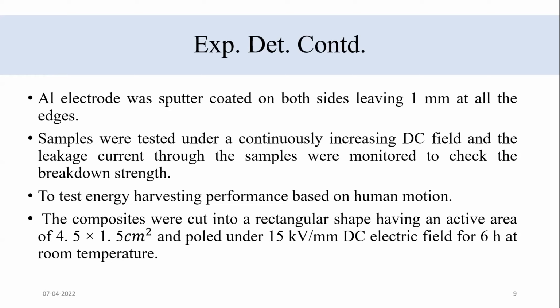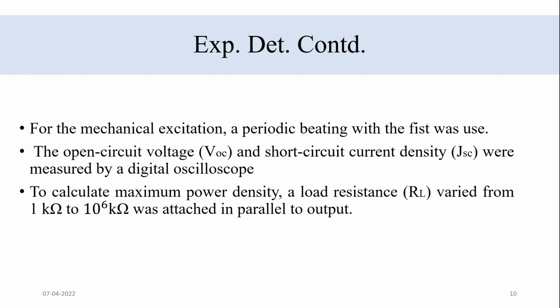I used beating of a fist for recording the mechanical energy. The composite film was cut into a rectangular shape having an active area of 4.5 by 1.5 centimeter square and poled under 15 kilovolt per mm DC electric field for 6 hours at room temperature. For mechanical excitation, a periodic beating with a fist was used.